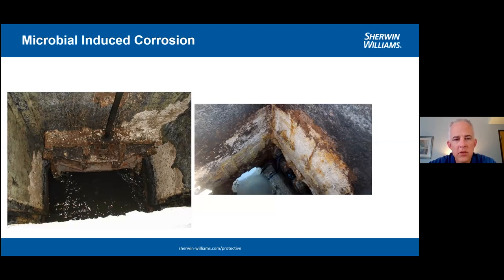In that photo on the left, you'll also notice down towards the bottom, because hydrogen sulfide gas is heavier than air, it lays on the bottom. You'll notice there on the bottom, the concrete deterioration is much more aggressive than it is as you come up the structure itself. If I remember correctly, I think we had lost about an inch to inch and a half of concrete there along the very bottom. A similar photo on the right is primarily a concrete structure. This one doesn't have the steel where I can show you that level of degradation.